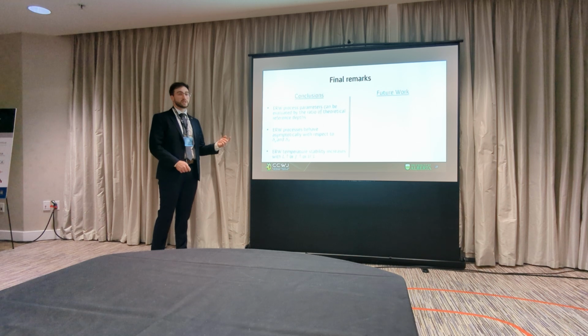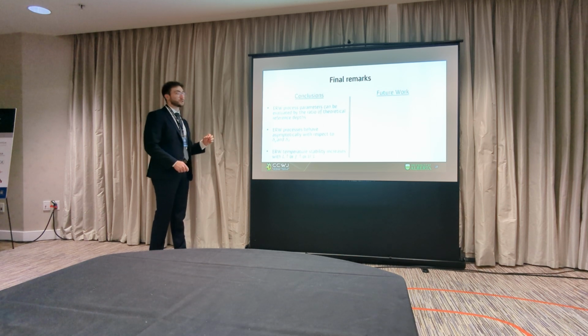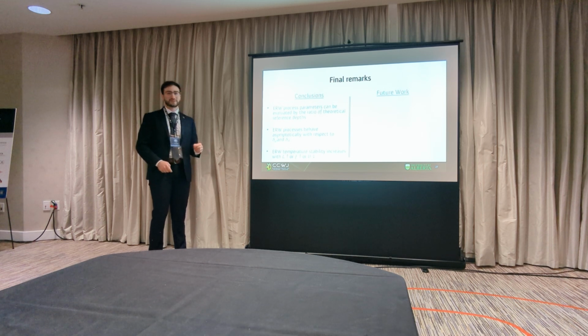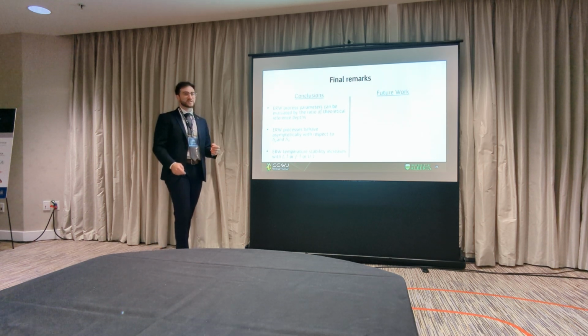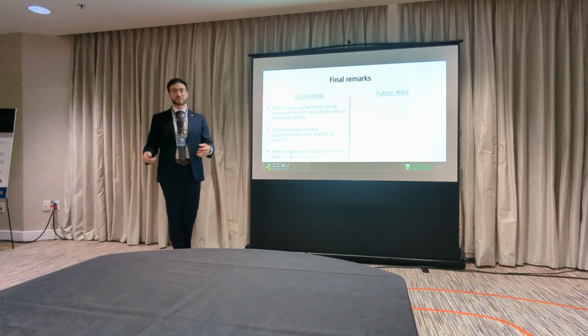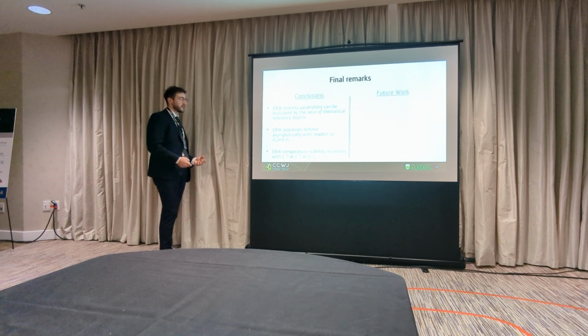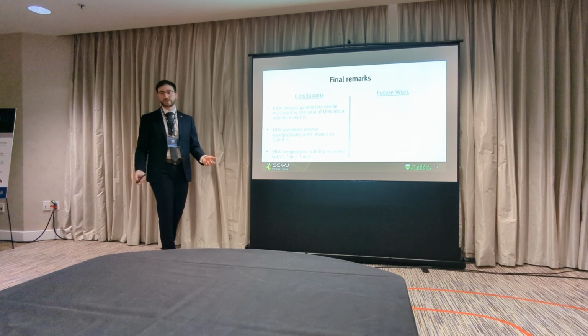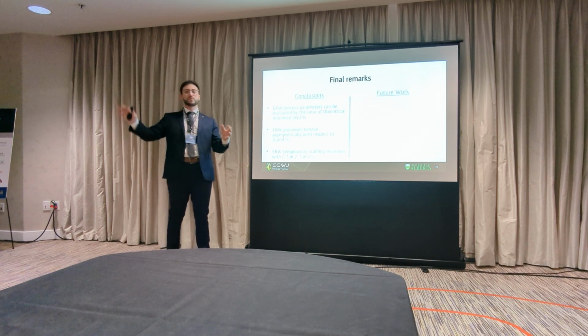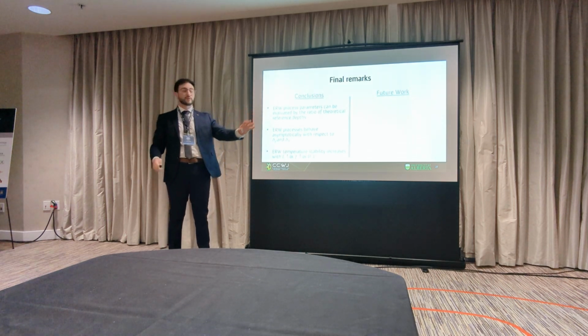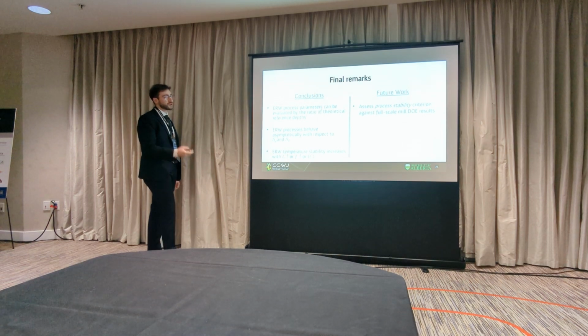ERW temperature stability at the weld point will increase as your V length increases, increase as your frequency increases, or increase as your mill speed decreases. A noteworthy thing is that all three of these are not cost effective. Your V length is sort of fixed by your machine. Having a higher frequency in your system requires a more robust and expensive electrical system. And then running at a lower mill speed reduces production. So there's some sort of optimal point between productivity and a good weld. For future work, there's 2 points I want to touch.